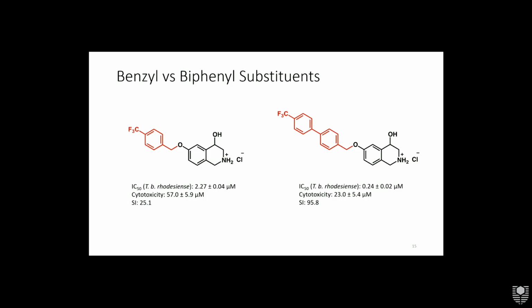And then I guess comparing smaller to larger substituents at this position, in almost every single case, our biphenyl substituents were much more active than the smaller benzyl substituents. You can see here again about a tenfold increase when we increase the size of that substituent. That did increase the toxicity slightly too, but our selectivity index is still far, far better. So, yeah, that was in every single case except one.